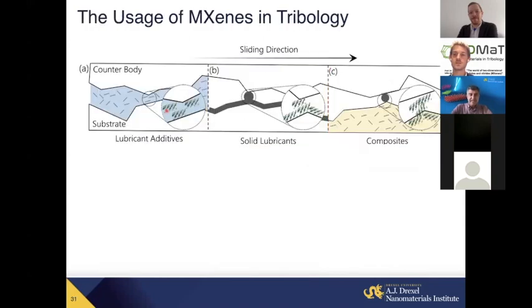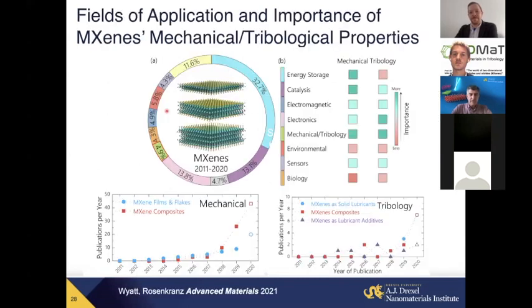Yes, you can also improve mechanical properties. I think the statistical analysis I showed you here shows MXene composite materials. Those are exactly these types of papers. There are probably many more actually, because many of them are for functional applications, not for mechanical applications. But yes, because of the stiffness. Moreover, let me also mention something. Because MXene has a surface termination and is a couple of layers thick, you can actually even covalently bond polymers to this material without losing its mechanical strength and conductivity, unlike, say, graphene, where it's not only very difficult to bond anything to the surface, but, for example, forming graphene oxide kills the conductivity of the material completely. Right.